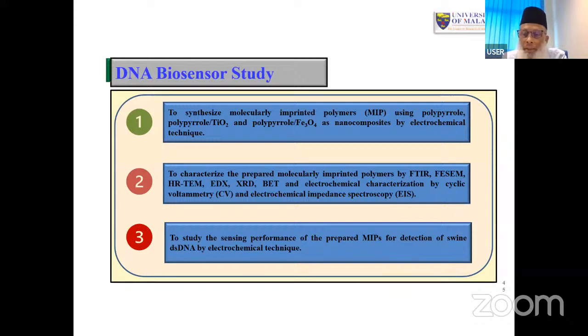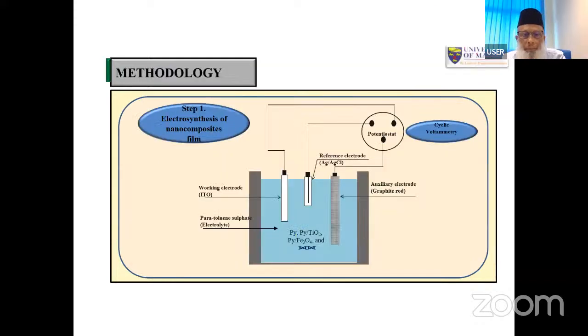Later, we characterized with the usual characterization techniques: FTIR for the structure, FESEM for the morphology, HRTEM again for the morphology, EDX to check whether the materials have the metals or not, XRD for the crystallinity, BET for the surface area, and the electrochemical characterizations. All these were done by cyclic voltammetry and electrochemical impedance spectroscopy, EIS. This study was also done to test the sensing performance of the prepared MIP for detecting swine DNA by an electrochemical technique. So this is the step that was followed for preparing the electrode MIP, molecularly imprinted polymer.